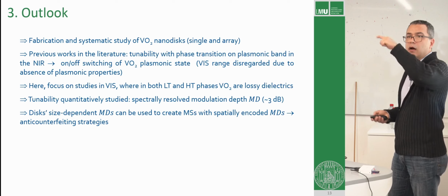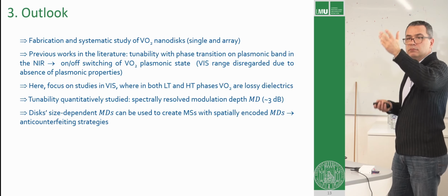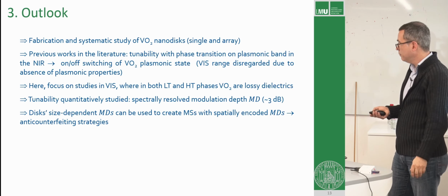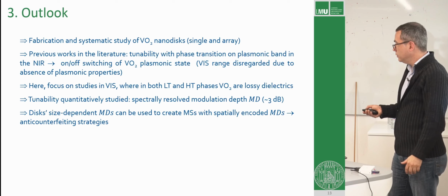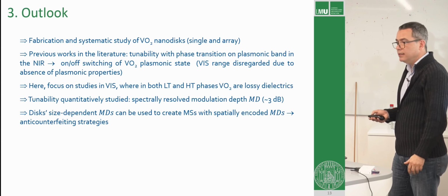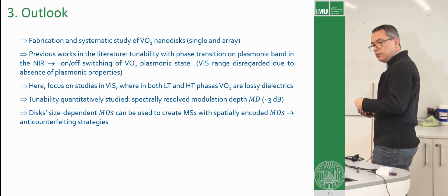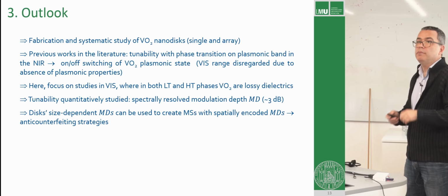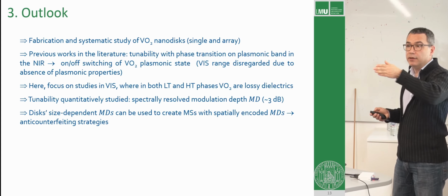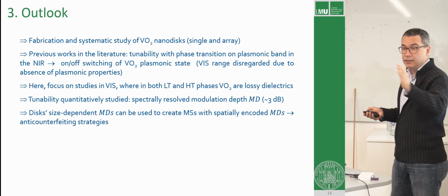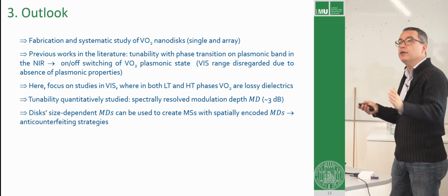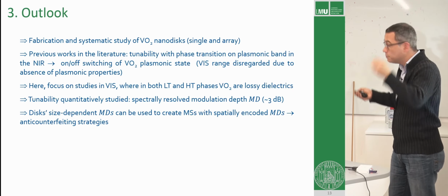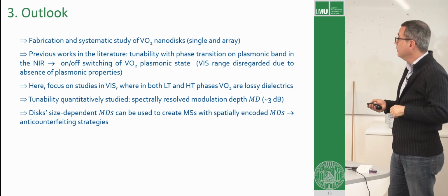This means how much the scattering changes in both phases, low temperature and high temperature. And we also showed at the very end that these modulation depths depend on the sizes, and this means that they will also be different for different wavelengths because the size of the particle is related to the Mie resonance and everything is based on the Mie response of these disks.